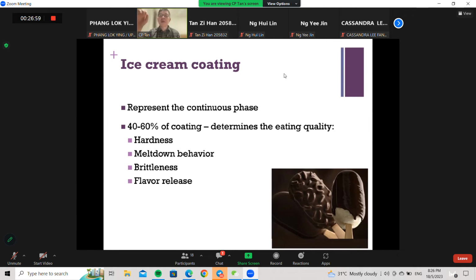Okay, so they cannot remain liquid for very long, because once they remove it, if they remain liquid for a long time, they are going to slide because of gravity. They are going to slide to the bottom. So then it will create an uneven thickness of the coating. I'm sure all of us enjoy Magnum. If you enjoy Magnum, you will always observe that the thickness of the coating is very homogeneous. Am I right to say that?